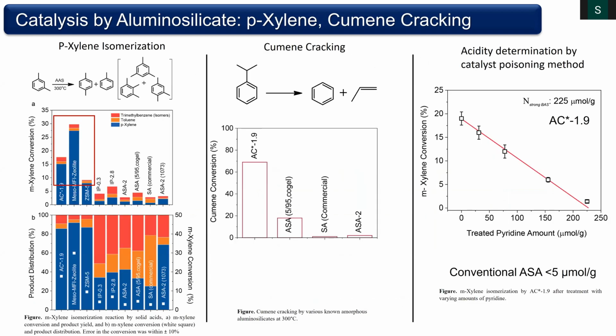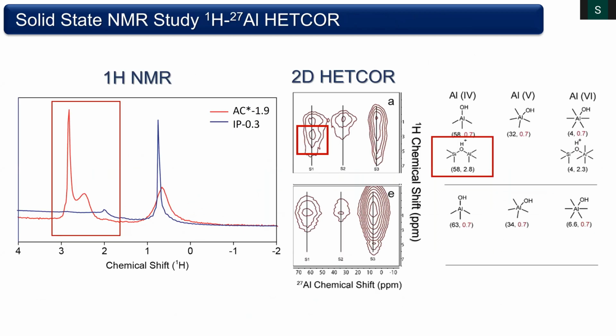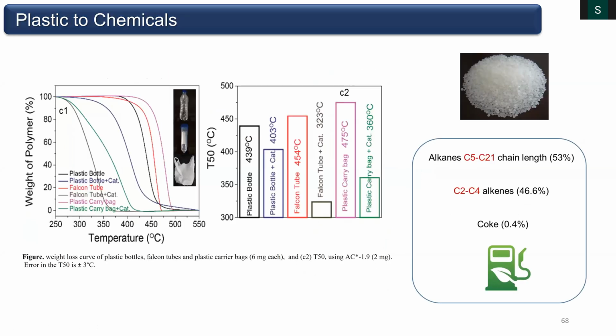I skip all of these, and we also use solid NMR to again show that there is this proton signal at 2.8 ppm, which is known for the zeolitic type bridging silanols, but we observe that in an amorphous material, indicating this is some sort of a hybrid amorphous aluminosilicate zeolite type material. And here we showed the plastic degradation.